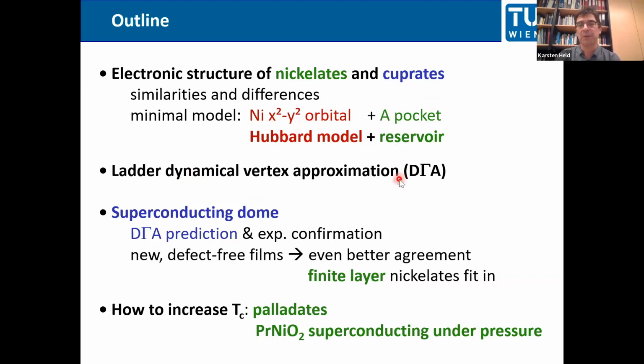We are then doing a D gamma A calculation, dynamical vertex approximation. And we predicted the superconducting phase diagram at a time where only the very first experiment from the last slide was available. And in particular, with the most recent defect-free films, the agreement with experiment is just breathtaking and much better than we dared to hope. And also finite layer nickelates drawn by Giulia Mundy nicely agree with that picture.